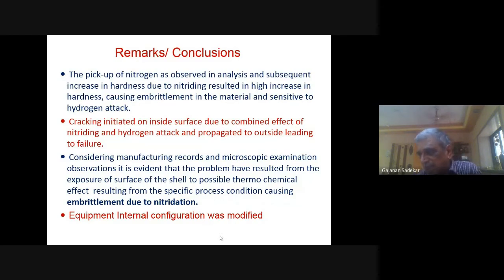This means the process gas has come in contact, which was not supposed to come in contact because there are some internals which are there. Those internals actually got damaged, and because the internals got damaged, that catalyst came in contact with the surface of the equipment, which has caused the reaction to occur on the surface of the equipment, and thereby the nitriding occurred and hydrogen attack occurred and the failure has occurred.